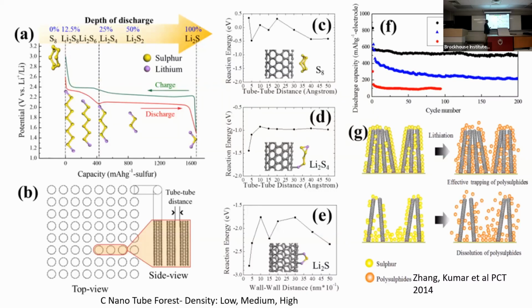You can vary that. And using the formulation, we clearly showed whenever you have this very high density, then you had not only high capacity, you have very stable cycling as well. And of course, if you purposely keep them all apart, far apart, then immediately, even though it's still stable, the structure is still stable, but it's very low capacity.